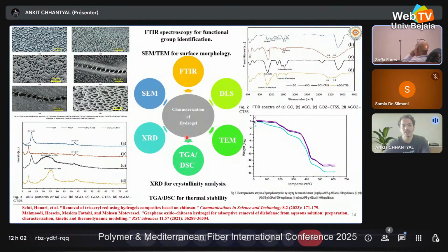And now the characterization of hydrogel involves FTIR, DLS, TEM, TGA, DSC, and XRD. SEM and TEM are quite similar, that they explain the morphology and topology of the system, but SEM provides the 3D image of the system, and TEM provides the 2D image of the system. But in the TEM, the material is encapsulated with the nanomaterials. TEM resolution quality is higher than SEM.